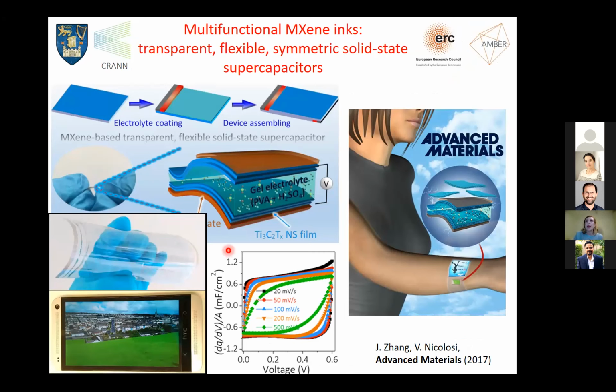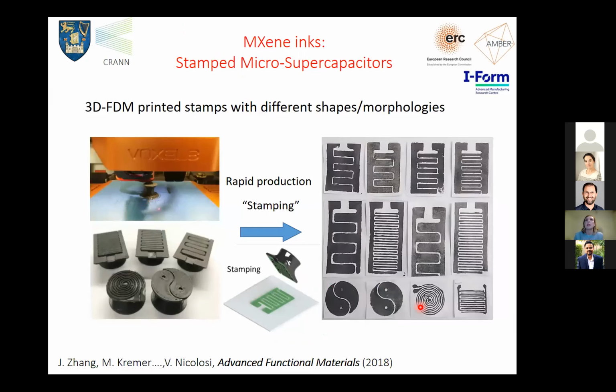For those of you who work with supercaps, you would know that it's very, very easy to make a tiny supercap, 1 centimeter by 1 centimeter. But it's very, very difficult to get a supercap of this size working. What you see here is a fully assembled supercap where you have 2 electrodes, the electrolyte sandwiched together, current collectors, and it's very flexible, extremely transparent, 99% transparency. And here it is superimposed onto my postdoc's mobile phone. It gave a very, very good electrochemical performance. Here you see the IV curves relative to these devices pushed up from 20 millivolts per second up to 500 millivolts per second. You see that there is no resistive behavior really. So that really gave us the confidence that this was a material that was indeed performing.